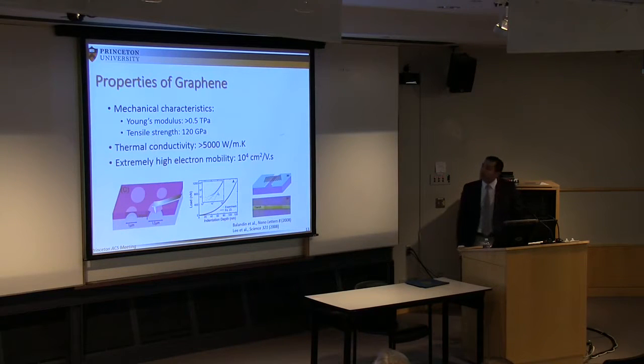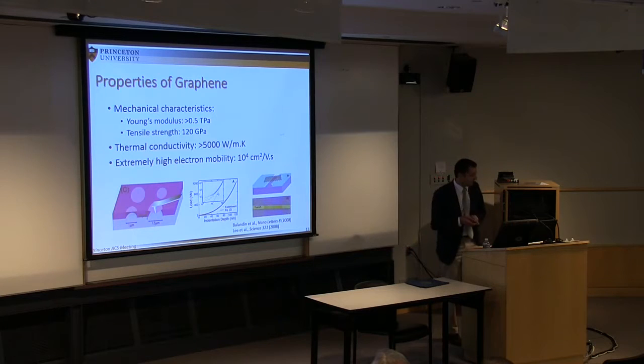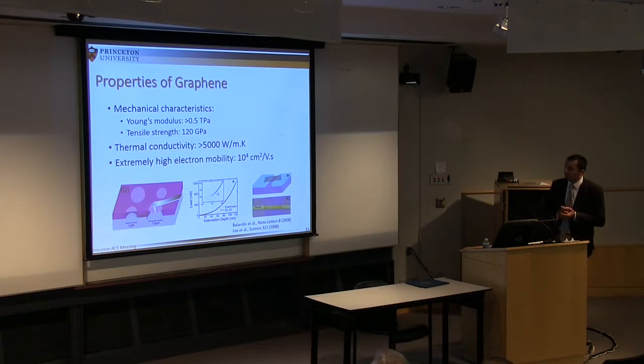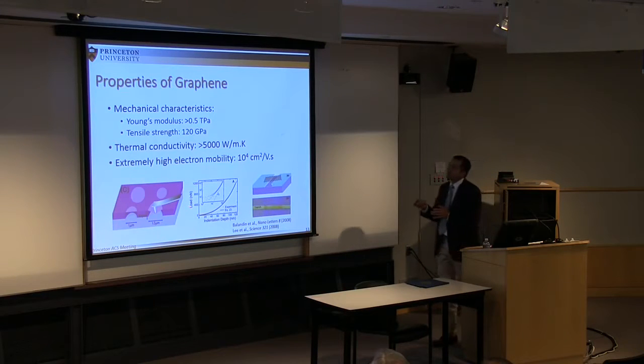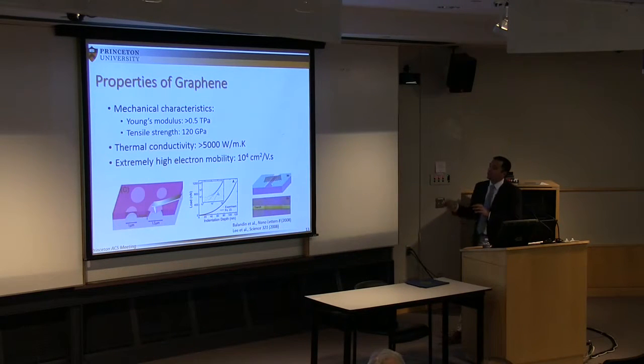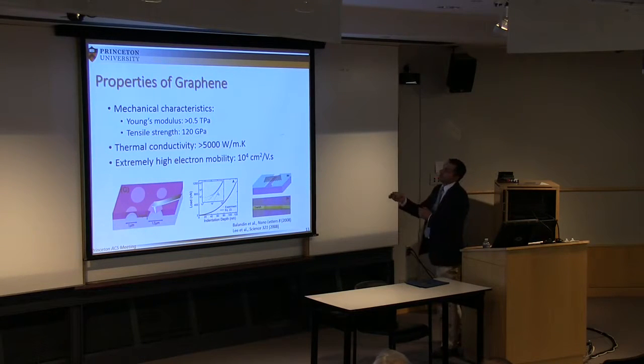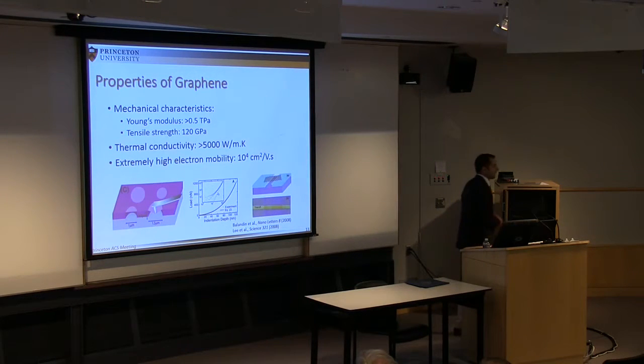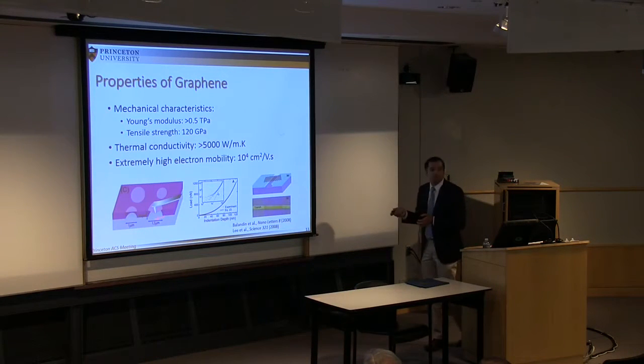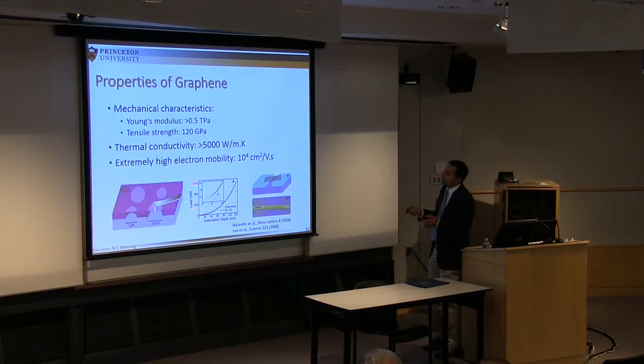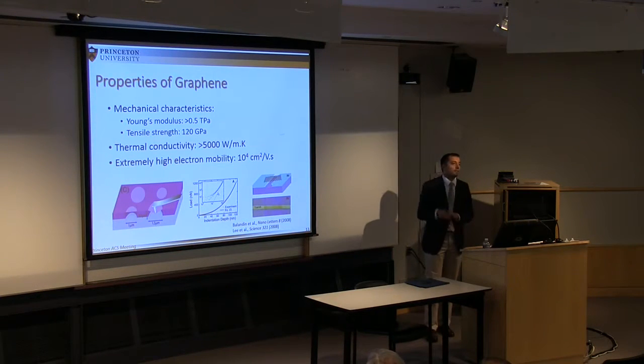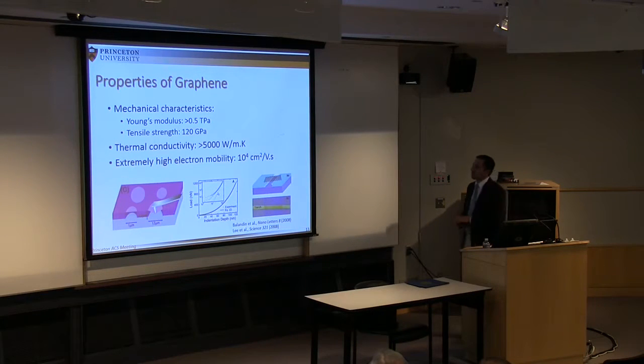Together with that, now if we talk about the properties, let's first focus on the mechanical characteristics. High skill is required for those types of experiments, because you have an insulating substrate, say, and then you need, for instance through photolithography, to make holes or trenches, and then suspend a graphene layer, and then you can start working on it. You can measure the mechanical properties of the material, just like a simple tensile experiment. So basically, you apply a load and measure the deformation of the material. From that, you can get the stiffness of the material and the tensile strength.